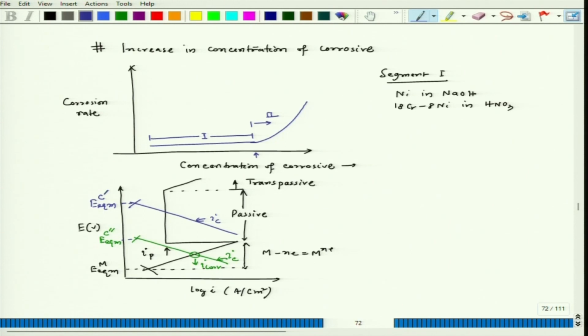Now, if we compare these two situations as per mixed potential theory, we have a very high corrosion rate which is located at this location. Fine. But somehow if we have some other oxidation or reduction process, or a cathodic polarization line that interacts with the anodic polarization line in the passive zone, then of course this becomes my I corr, which is equal to IP, the passive current density, which is much lower than the I corr we observed where the cathodic and anodic polarization lines interact in the active zone, but here it is interacting in the passive zone.